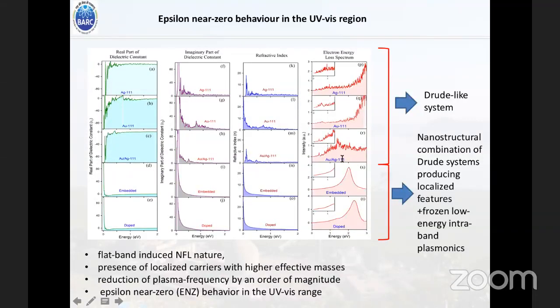And look at the electron energy loss spectrum, there are intraband plasmons present in the system. But in these last two systems, there is epsilon near zero behavior for the UV-vis energy range, starting from the UV energy range to the visible energy range. There is a near zero epsilon behavior present in the system, and also all kinds of low energy intraband plasmons are frozen for these systems. And there is an interband plasmon peak only present here.